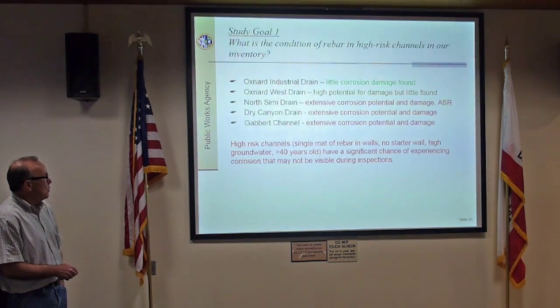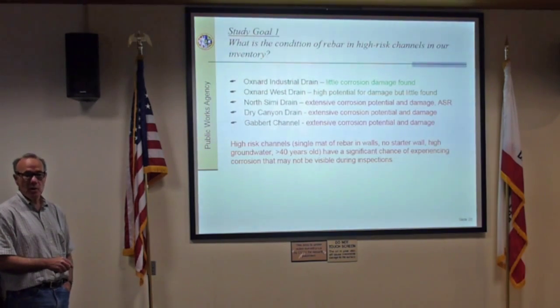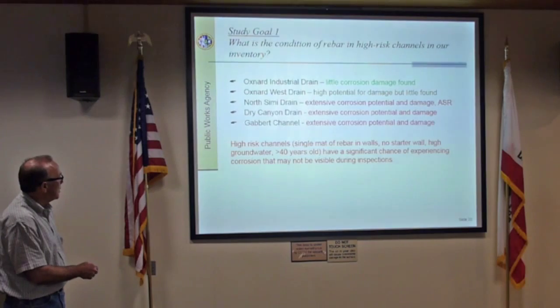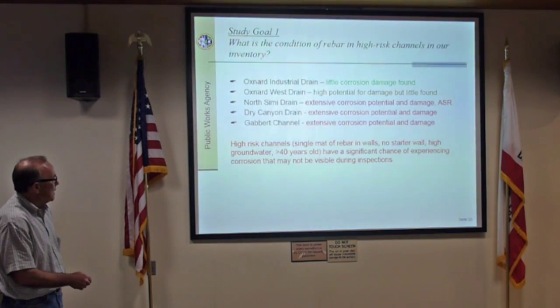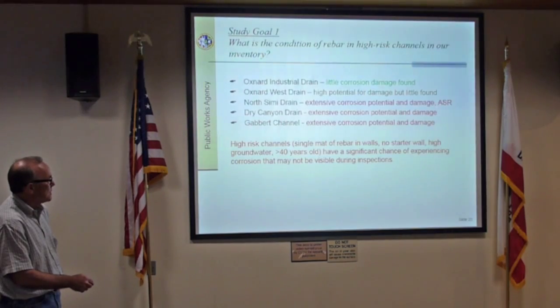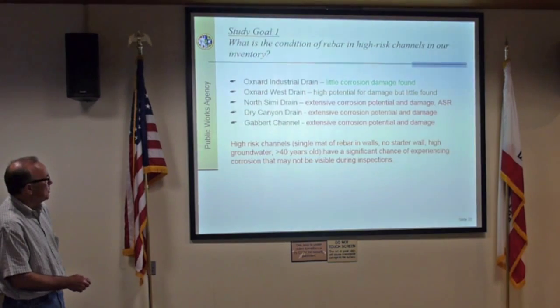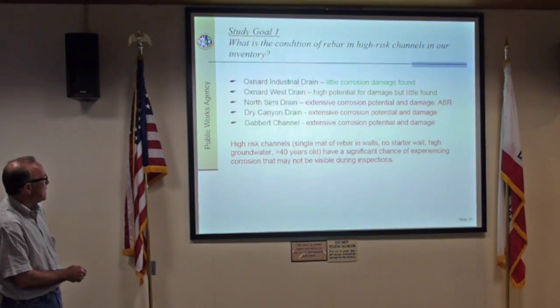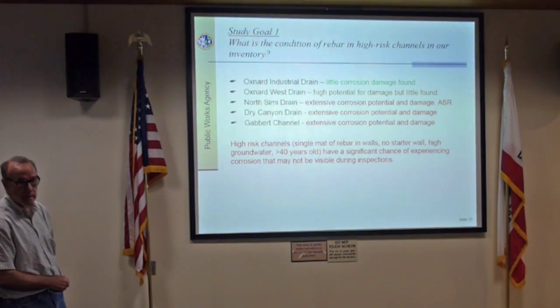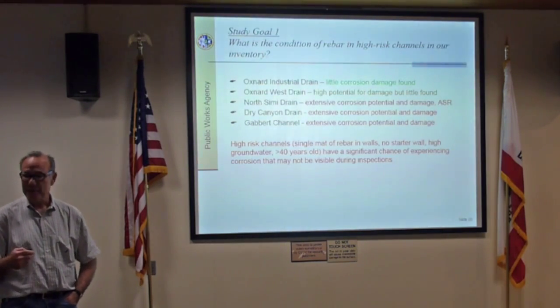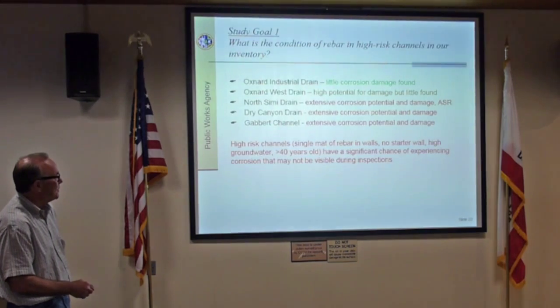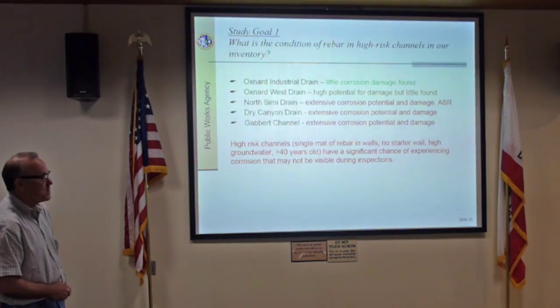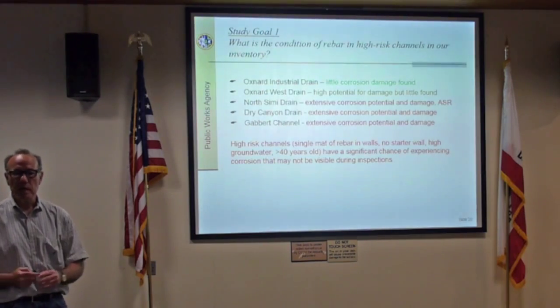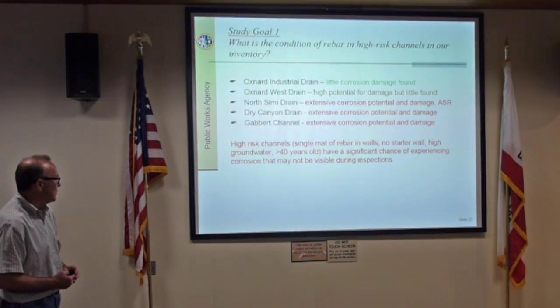North Simi Drain, we found both extensive high potentials and damage and some ASR. So this one was ripe for corrosion. Dry Canyon Drain, high corrosion potentials and damage. Gabbert Channel, high corrosion potentials and damage. So the only one that's a little bit misleading from our non-destructive tests was really the Oxnard West Drain, which is where the panel fell. We had high potentials. All the indicators were there for a lot of damage, but we did not really find a lot of additional corrosion damage in those particular areas.